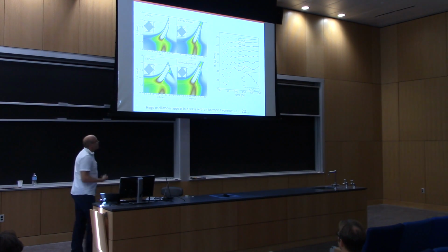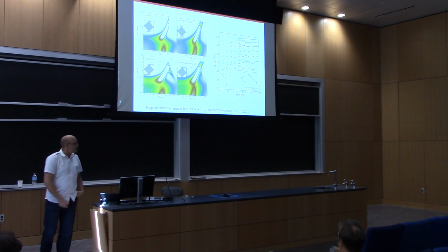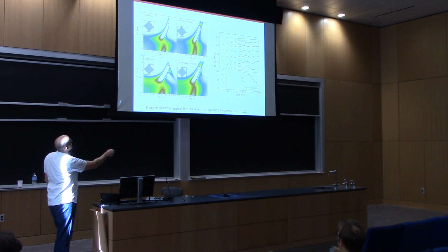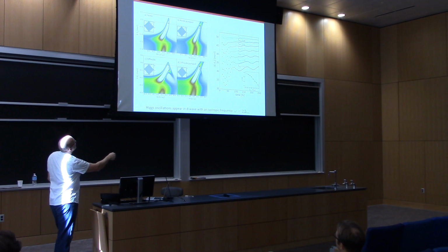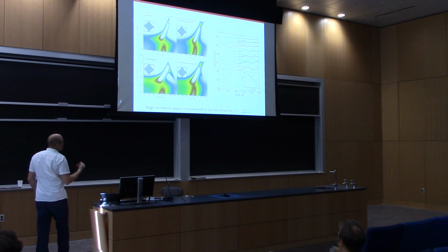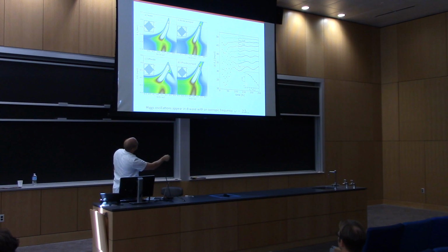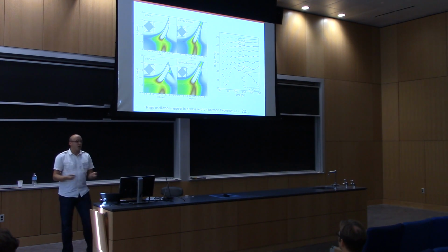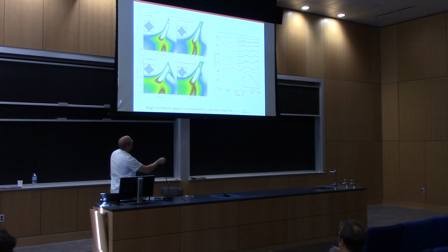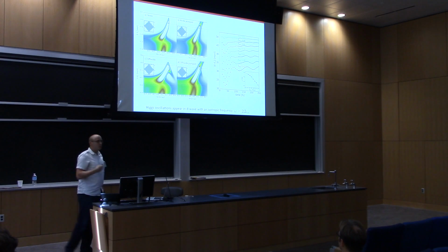So we can do the same game where we do this as a function of fluence. Right, for very weak fluence, I make small changes, and I get very weak oscillations. For larger fluence, I make big changes, and I see bigger and also slower oscillations. So you can plot the oscillation frequency as a function of, in our case, applied field. Really, you can convert that to how much energy is absorbed. And this extrapolates out in some simple polynomial form to the equilibrium delta, as it should.